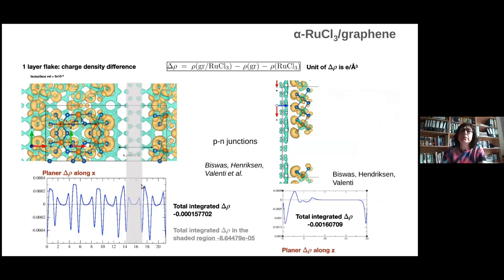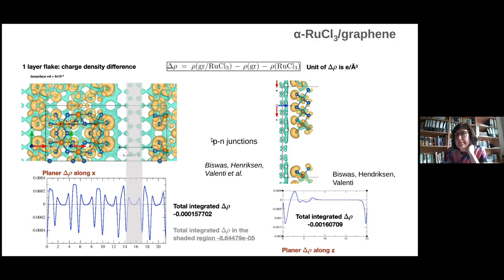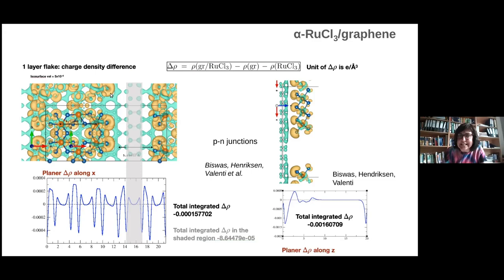What we are now doing is using the charge transfer properties between alpha-RuCl3 and graphene, which seem rather optimal for these heterostructures, to build PN junctions — together with Eric Henriksen in the U.S. By this type of heterostructure, one can very nicely tune to produce PN junctions. Even though the Kitaev physics is not at the forefront in these PN junctions, what is at the forefront are the charge transfer properties of alpha-RuCl3.